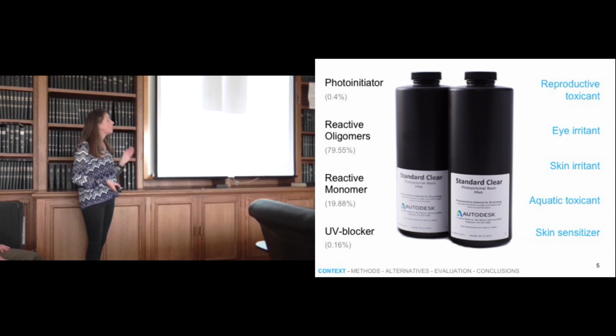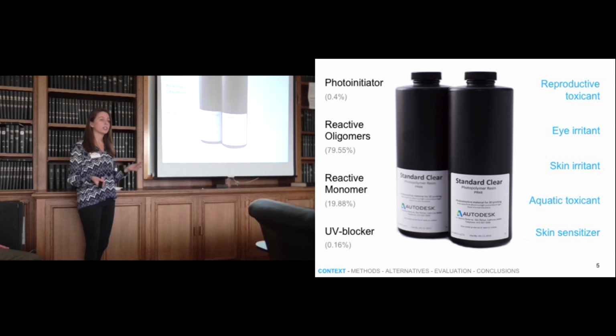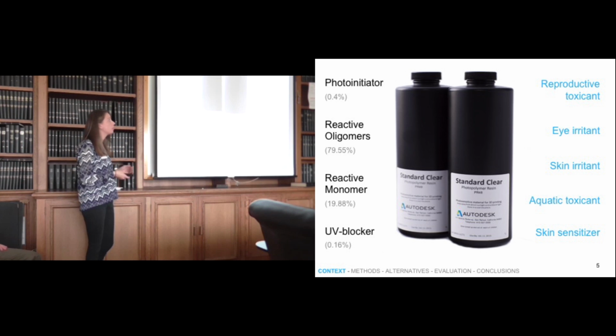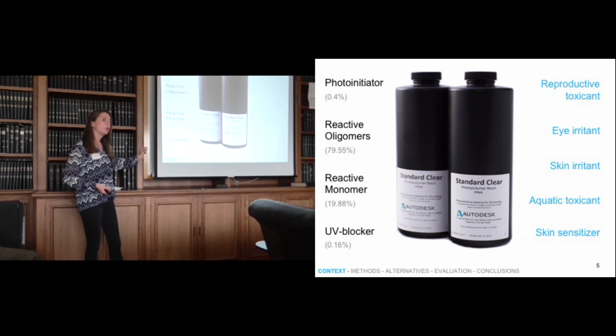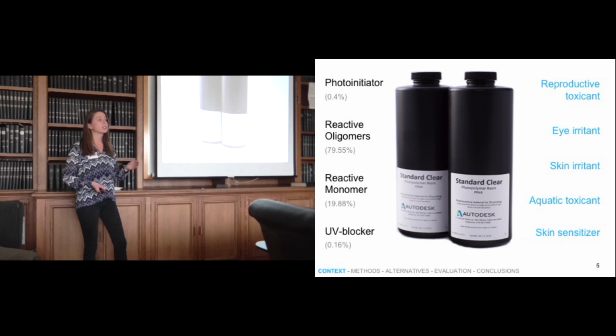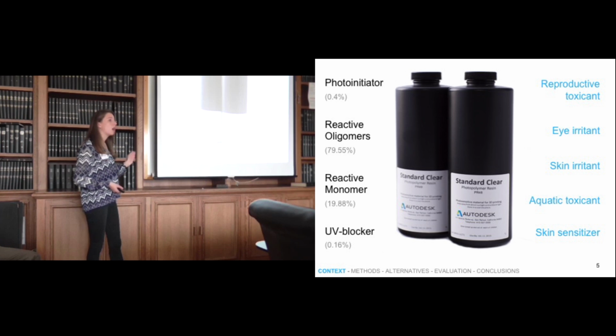If you start at the top, you can see the photo initiator, a very small component of the overall resin, allows for the initiation of the polymerization process. It starts the activation of that phase change, allows it to begin converting from the liquid polymer to the solid printed product. The reactive components here allow for more cross-linking, build on the strength of the product, allow for the product to build upon itself as it's created. And finally, the UV blocker, again, at the bottom, another small component of the overall resin. It's actually absolutely essential when you're looking at the resolution. You need to be able to block some external UV. You only want to be focusing in on the area that the computer software has dictated the light should show to convert, again, the liquid resin to a solid polymer.